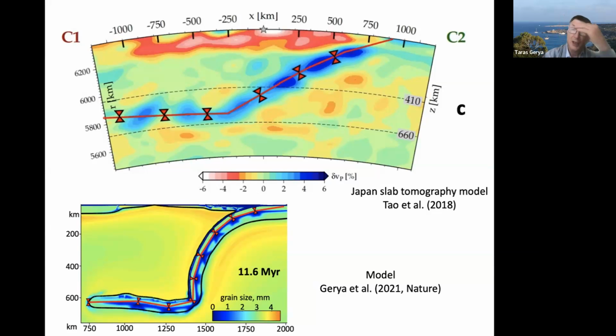And moreover, as in the case of this Kit Kat chocolate, positions of segment boundaries inside slabs are not random, and they do not change randomly along the trench. If it were inaccuracy of mantle tomography, we would see them all the way around, but they always stay more or less at the same length of the slab counted from the trench. So essentially this Kit Kat chocolate picture is preserved in the mantle tomography. And this was very striking.